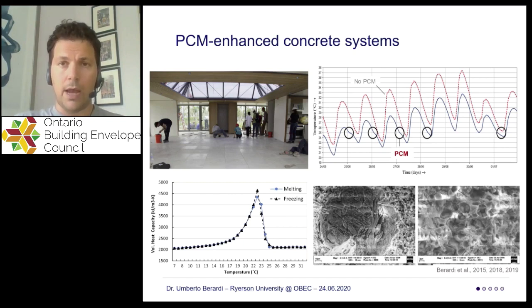And here you see on the right with the red curve, the temperature profile of the house without a PCM. And you can see how easy it was to reach 35, 36, 37 degrees in one week. And then you can see at the bottom a following week with completely similar outdoor conditions. But once the PCM concrete floor was introduced, then you start seeing this stabilizing temperature profile, which doesn't really